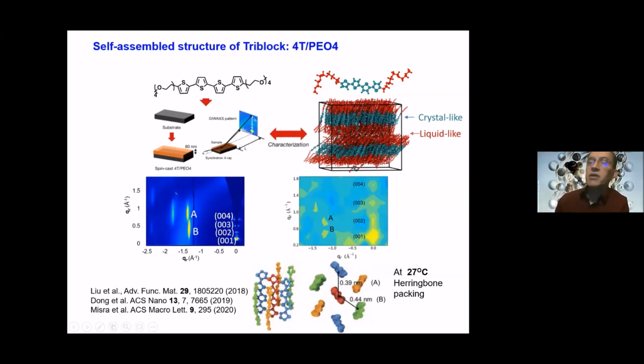But that dual characteristic is actually great for our application, because if you want to conduct electrons, you rather do it in a crystal-like material, because electrons are conducted by this sort of quantum mechanical effect of resonance or particle in a box. While if you want to conduct ions, they move basically through Brownian motion, so you want an environment that's very mobile, very liquid-like. So this structure turned out to be great for the application, and in fact, we have measured that. They have also measured this, and we found that it has excellent dual conductivity that's better than any other material that has been produced so far. So we're very happy about this result, and of course we want to optimize it.